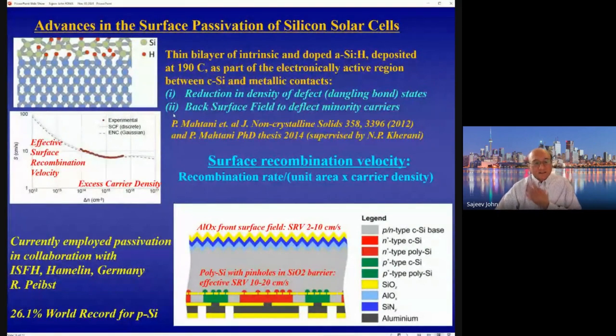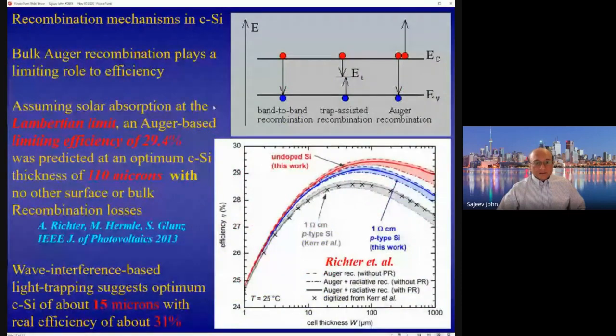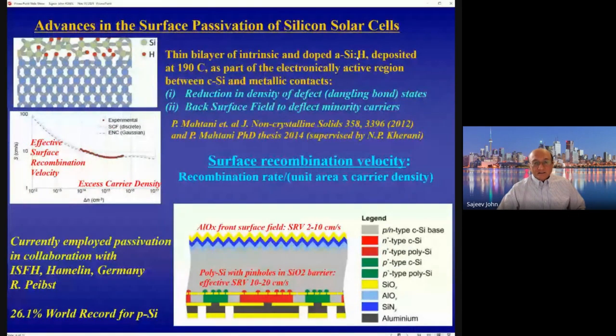So one that has been used by a colleague of mine at the University of Toronto, Professor N.P. Kherani, is to deposit a thin layer of both amorphous hydrogenated silicon that is heavily doped and also a small layer that is undoped. What that does is that the hydrogen can cap these dangling bonds, and the heavily doped amorphous hydrogenated silicon creates donors that can create an electric field at the surface, which prevents one of the carriers from reaching the surface.